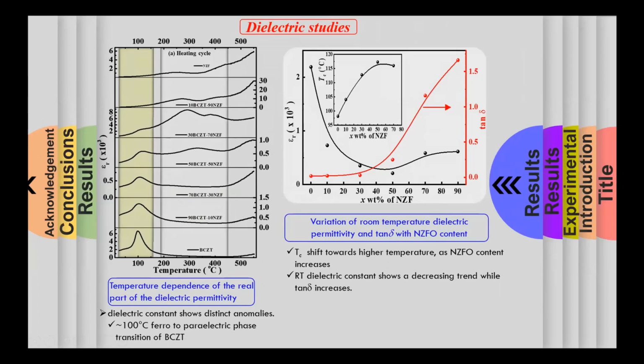90 weight fraction of piezoelectric phase plus 10 weight fraction of nickel zinc ferrite. Okay, this is a composite. In this one, it is only 70 weight fraction of the piezoelectric phase and 30 weight fraction of nickel zinc. So in this case, the piezoelectric weight fraction is much less as compared to this.